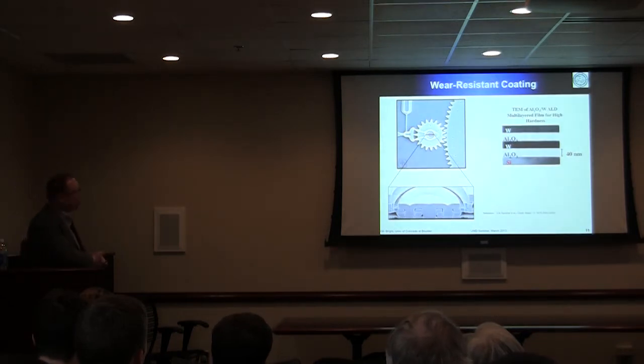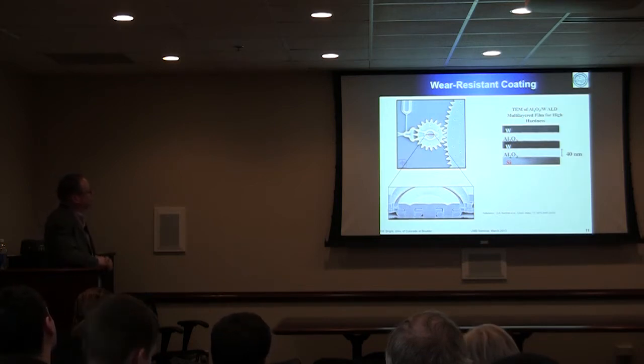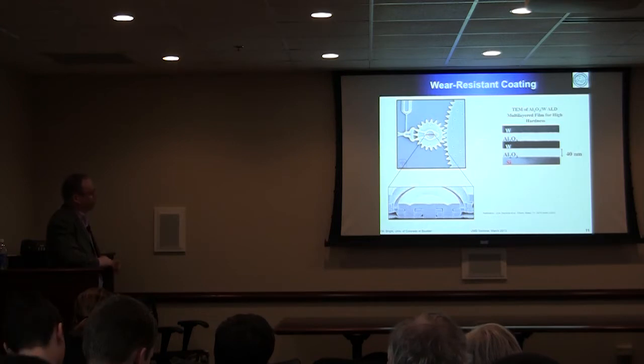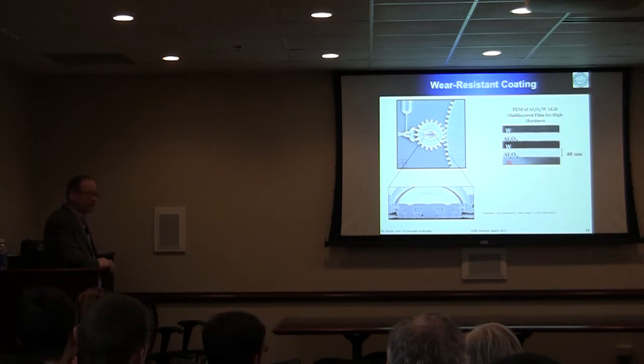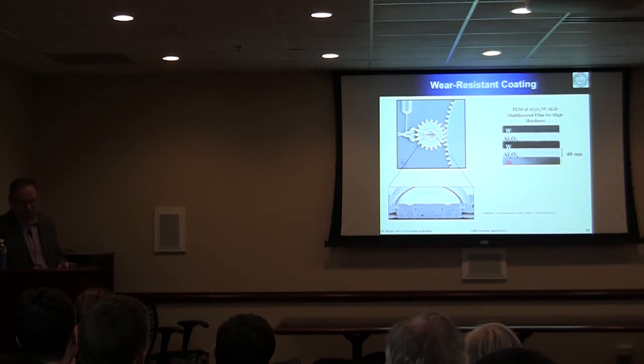Also a similar concept, aluminum oxide tungsten type coatings for wear resistant coatings. This is work done with Sandia. A while ago, they used to make these micro machines, and the silicon grinding against silicon would basically wear themselves out. So you can coat it with ALD material and have an improved lifetime of the device.